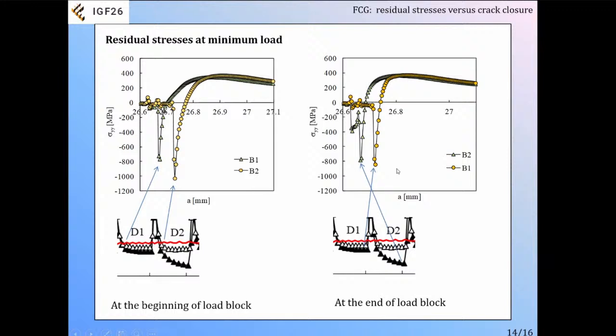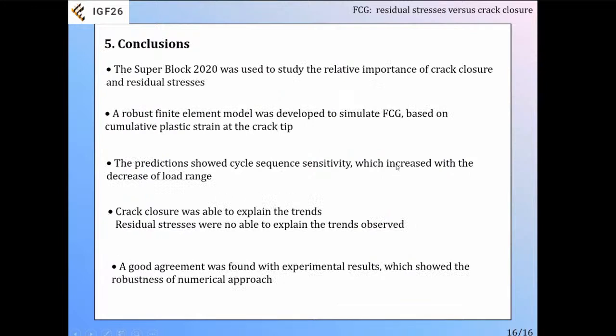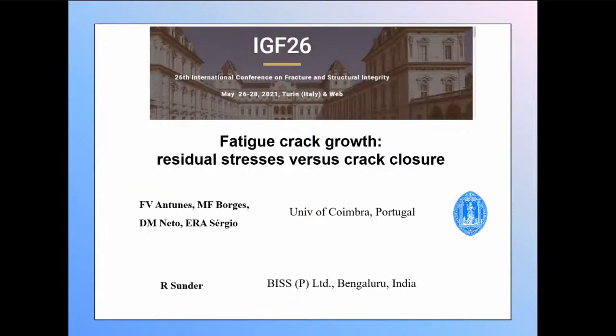So the conclusion is that the residual stresses cannot explain the trends, and the crack closure is the main phenomenon responsible for the trends we observed numerically and also experimentally. Okay, and that's all.